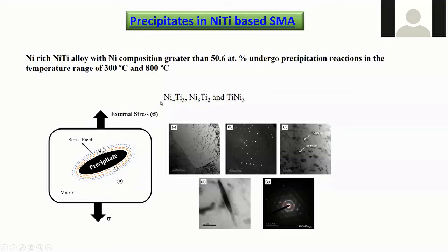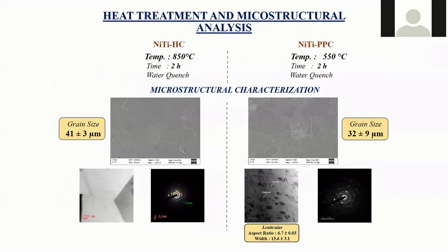For that we knew that if we do a heat treatment in the temperature range of 300 to 800 degrees centigrade, we are supposed to form nickel-rich precipitates. And if these precipitates are forming, then that is influencing the stress level. So if there is a precipitate, there is a localized stress that is forming, and there is a strain mismatch between the precipitate and the surrounding matrix, and that can lead to differences in the pseudoelastic behavior. So we started with the same one without any heat treatment.